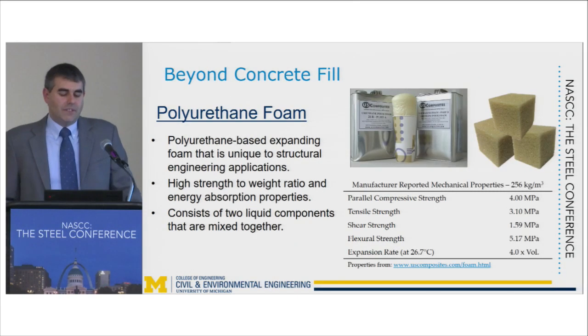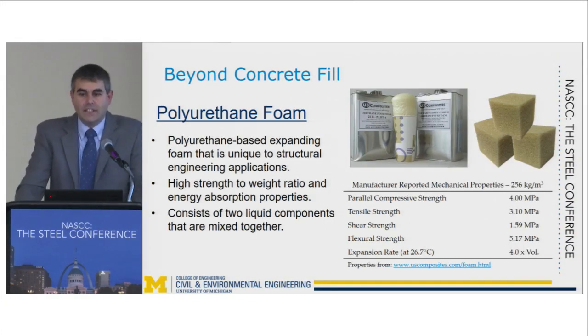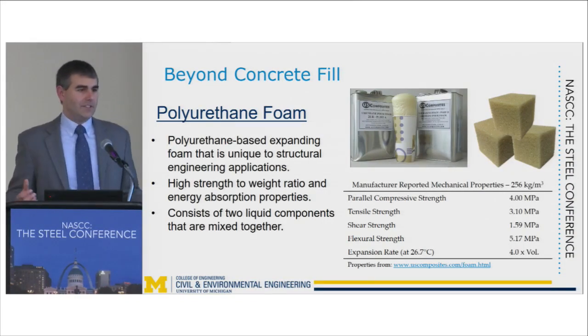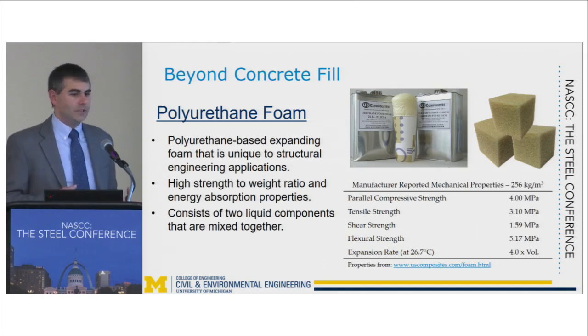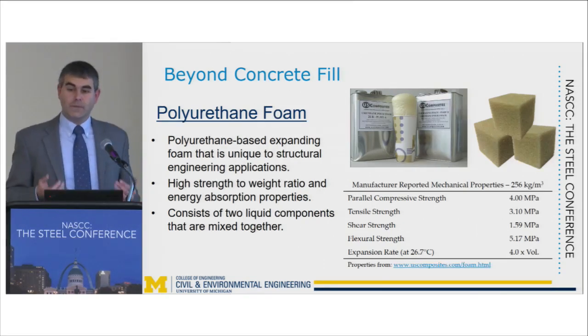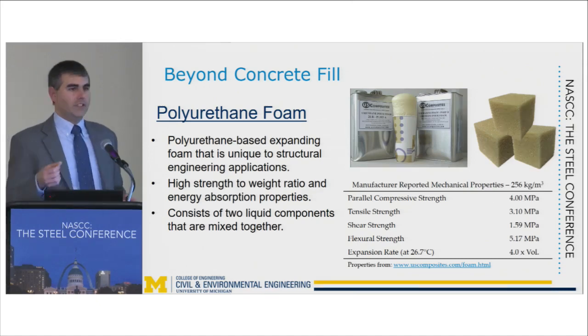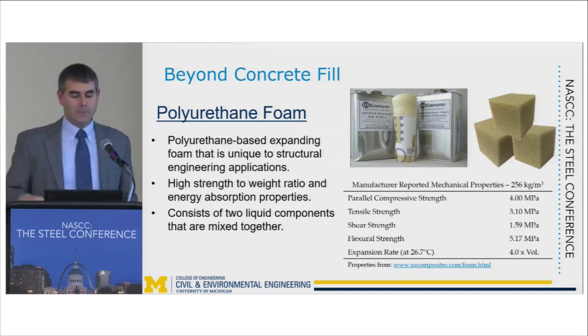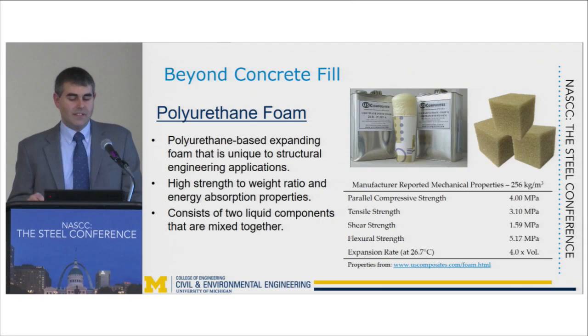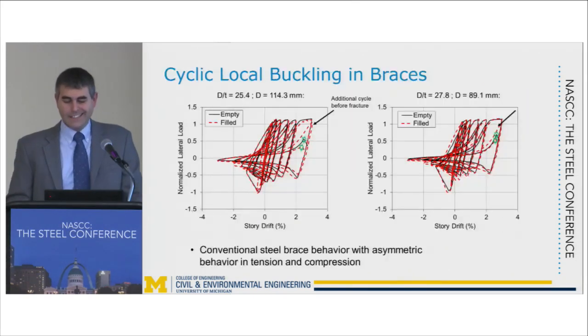And what we came across was this fairly stiff polyurethane foam. It's actually a two-part liquid that expands in place, so it works very, very well for a hollow structural section. Also, it could work for retrofit applications because you could just add a small hole, pour it in, it would expand in place and fill up that section. And we've looked at applications for HSS braces and HSS beams because I've done some work looking at complete HSS column and beam connections where you have a moment frame that's completely essentially tube-based.